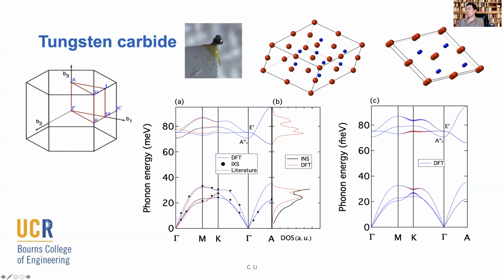What does that tell us? If you look at the right-hand side, we plot the angular part of the phonon momentum, and you realize those momenta reach their maximum value at this K point. If we visualize those phonon modes, it turns out those two phonon modes are 100% circular, which means one of them corresponds to a right-hand circular motion for one set of the atoms, and the other corresponds to a different circular motion. Those two modes are non-degenerate. They have slightly different energies, and that energy difference is something we can resolve with inelastic scattering.